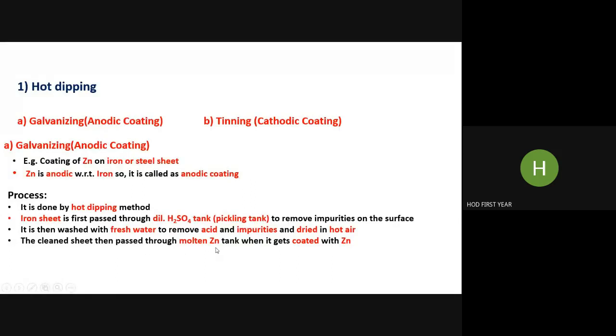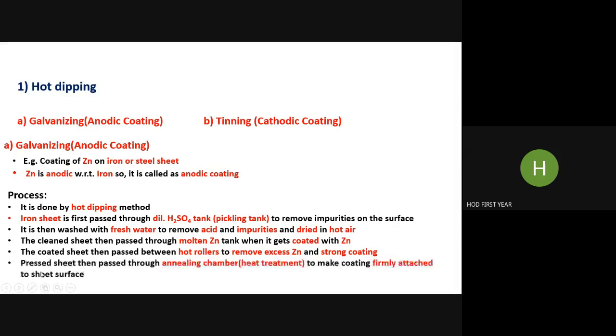The clean sheet is then passed through molten zinc. Once surface is prepared properly by cleaning, it is passed through the molten zinc tank where it gets coated with zinc. Those coated sheets then pass between hot rollers to remove excess zinc and to have a good contact between the article and zinc coat. Strong coating. After the rollers, annealing, which means heat treatment, is given. These sheets pass through the annealing chamber, heat treatment chamber, to make the coating firmly attached to the sheet surface.